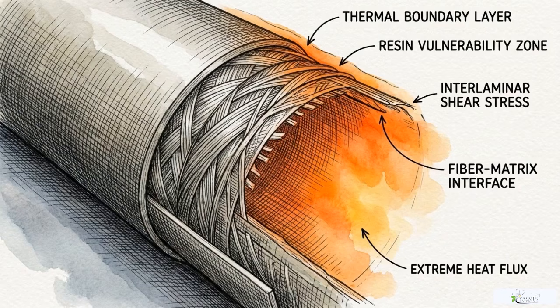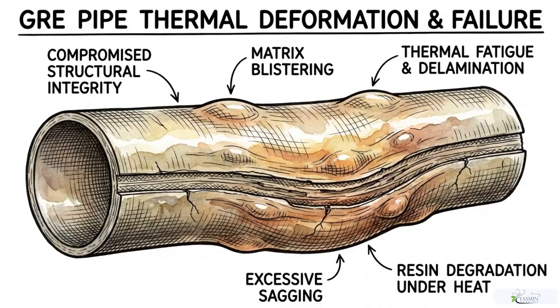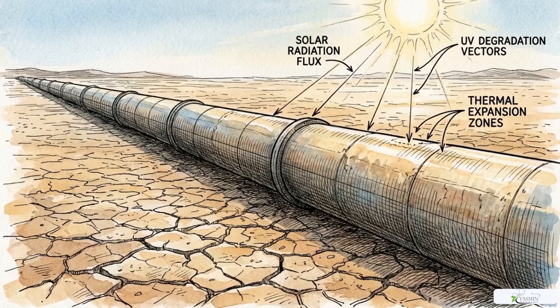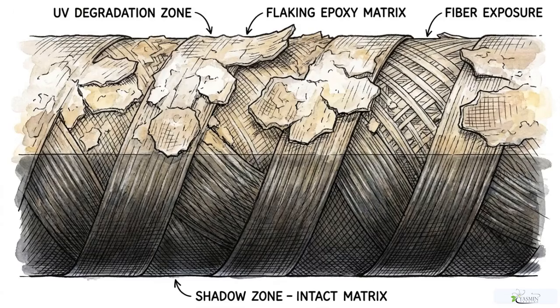However, that same epoxy resin creates a distinct vulnerability. It is highly sensitive to heat. Once the fluids inside the pipe or the ambient temperature outside exceed 130 degrees Celsius, the resin matrix loses its structural integrity. The pipe will start to soften and warp. It also struggles with prolonged direct sunlight. Unless you specifically purchase a UV-resistant variant, long-term exposure to ultraviolet light will gradually degrade the pipe's outer layer. While GRE permanently eliminates rust and chemical corrosion from your maintenance log, it dictates strict environmental boundaries regarding heat and sun exposure.